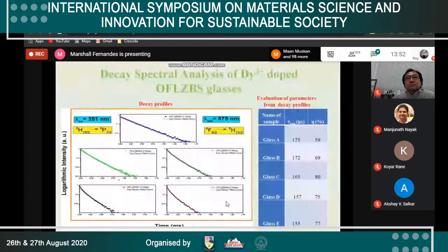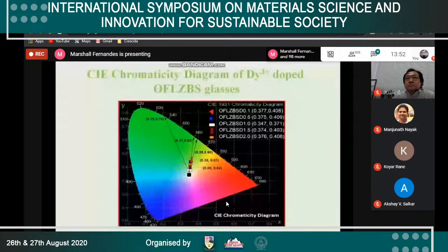By fitting these curves, we obtain the experimental lifetime, and by calculating the ratio of experimental and radiative lifetimes, we obtain the quantum efficiency. We can see from here that glass C is highly efficient. Now to measure the effect on color luminescent emissions of these glasses, CIE chromaticity coordinates have been estimated from PL profiles. Among all the prepared glasses, glass C possesses outstanding white illuminance coordinates at 351 nanometer excitation, which is equivalent to standard white illumination level.